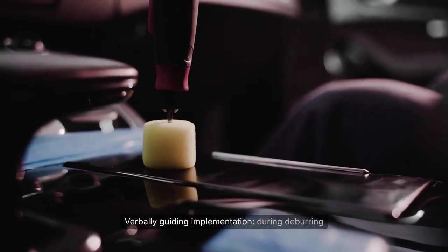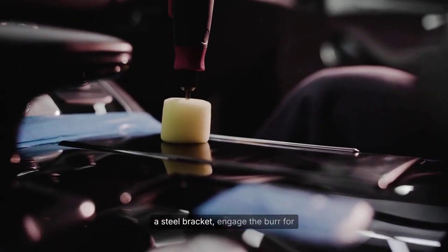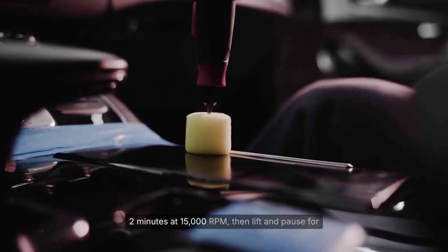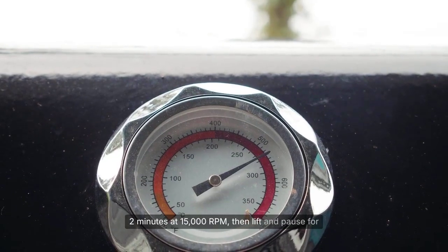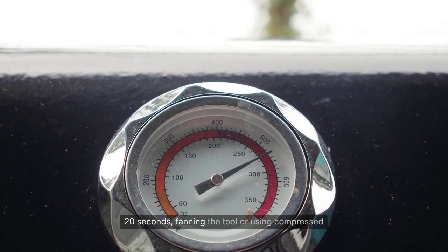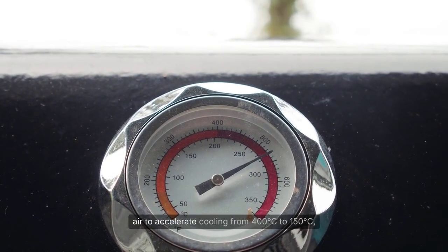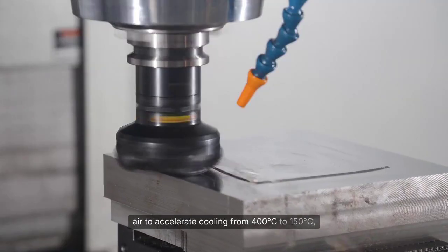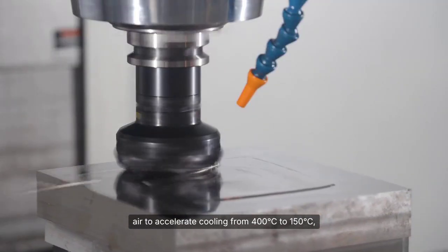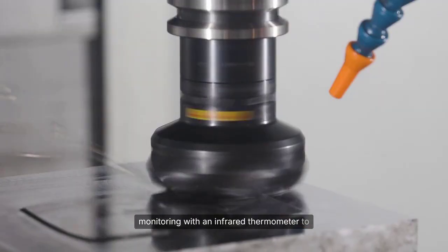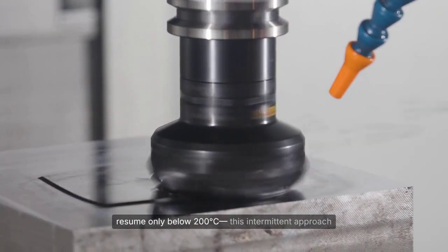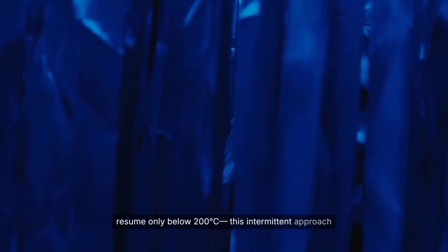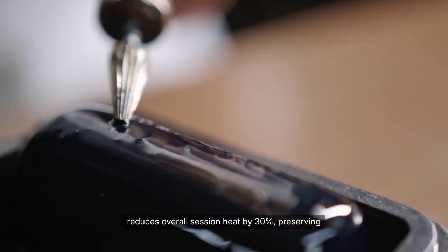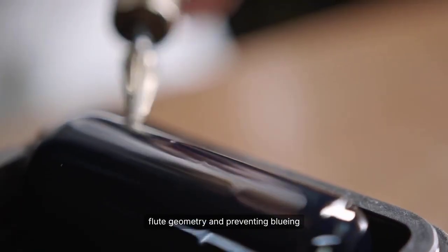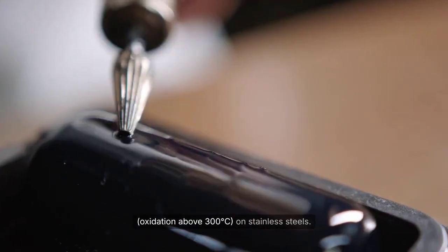Verbally guiding implementation. During deburring a steel bracket, engage the burr for 2 minutes at 15,000 RPM, then lift and pause for 20 seconds, fanning the tool or using compressed air to accelerate cooling from 400 degrees Celsius to 150 degrees Celsius, monitoring with an infrared thermometer to resume only below 200 degrees Celsius. This intermittent approach reduces overall session heat by 30%, preserving flute geometry and preventing bluing, oxidation above 300 degrees Celsius